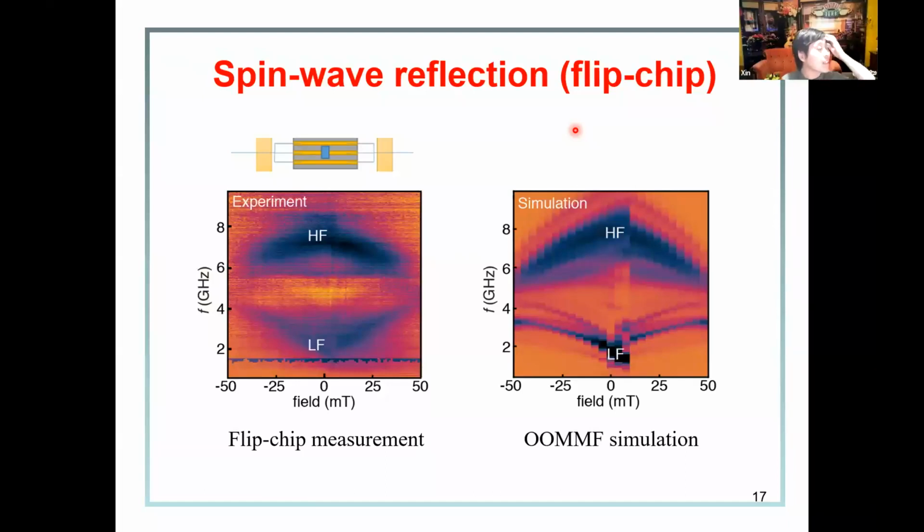Right, I see. You refer to this mode as the antiferromagnetic-like mode, where in an antiferromagnet the exchange coupling constant is negative. But in your system it's still a ferromagnet, so strictly speaking the exchange coupling is still a positive number, right? It feels to me that the reason it forms an antiparallel configuration is to minimize the dipolar energy, so the coupling is still dipolar mediated. But I guess you also estimated that the dipolar field is not strong enough to produce that high frequency mode. So that's actually quite interesting.